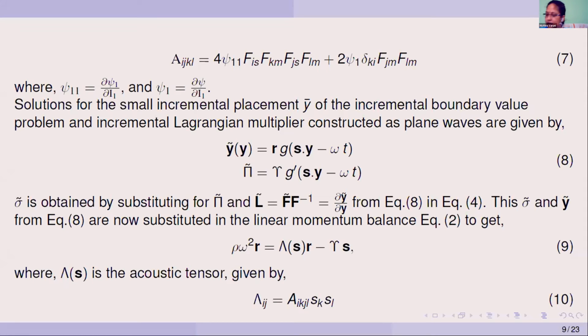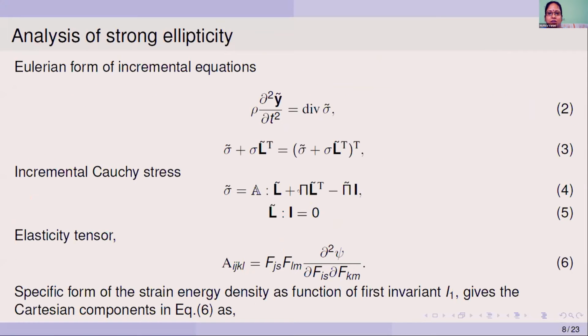And here in this equation for Lagrange multiplier pi tilde, this upsilon is the amplitude of the incremental Lagrange multiplier, and this g dash is the derivative of the function g with respect to its argument. So now we calculate this incremental velocity gradient L tilde from its definition F tilde F inverse using this expression for y tilde. And then we substitute this incremental velocity gradient back into this equation for the Cauchy stress tensor, and we obtain the incremental Cauchy stress.